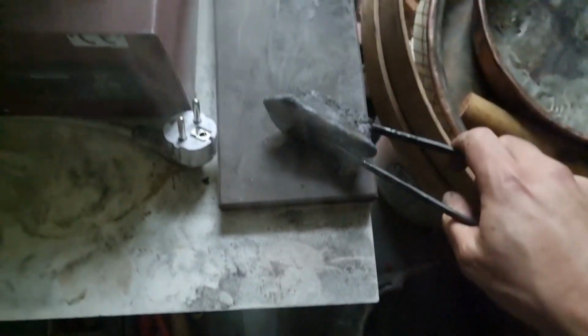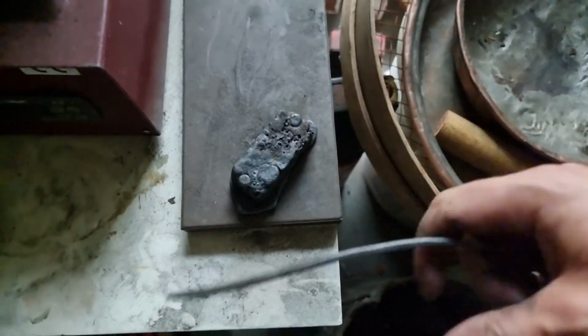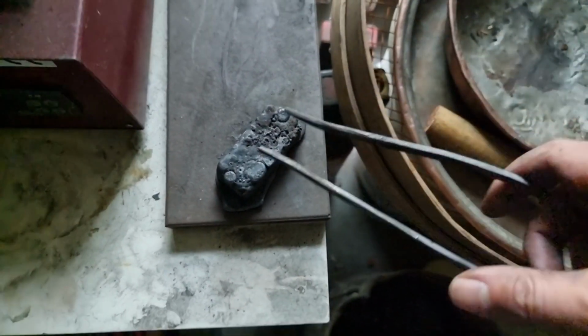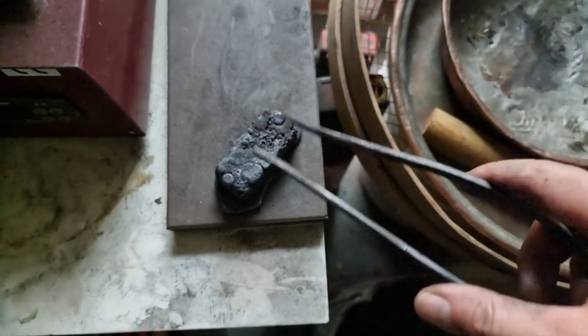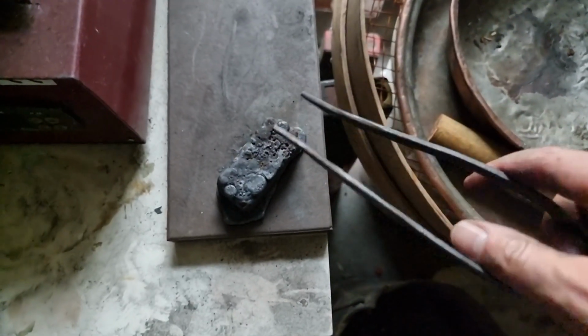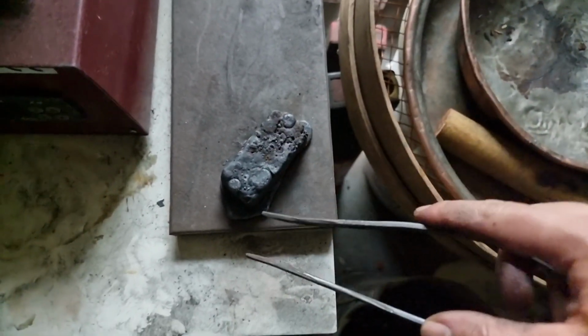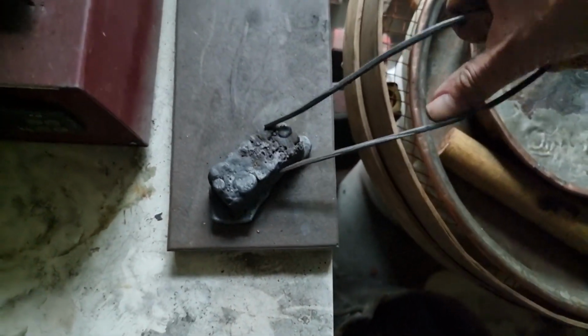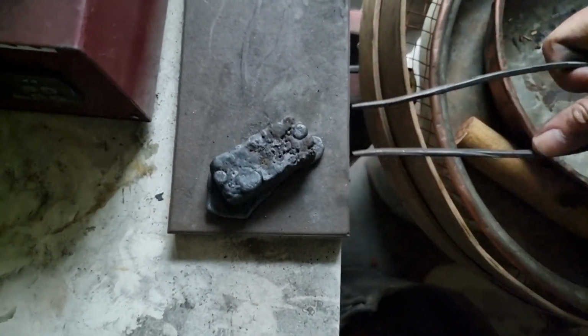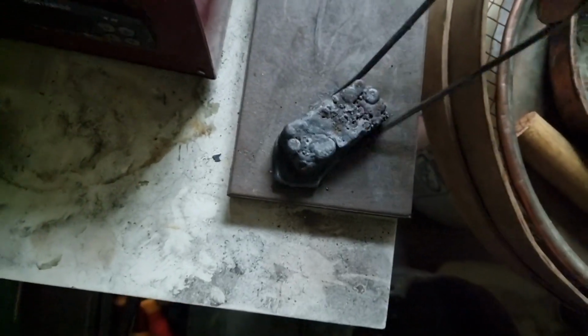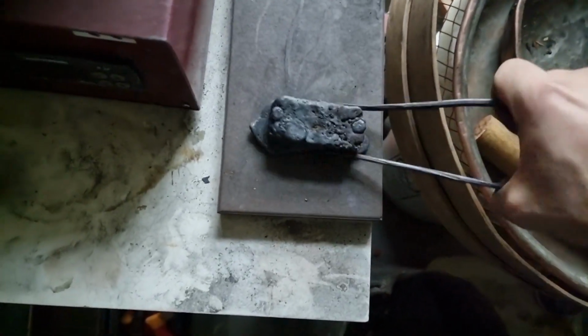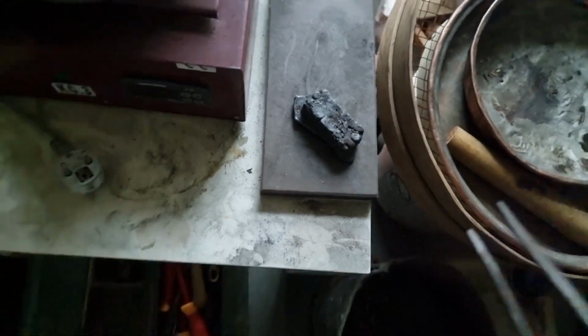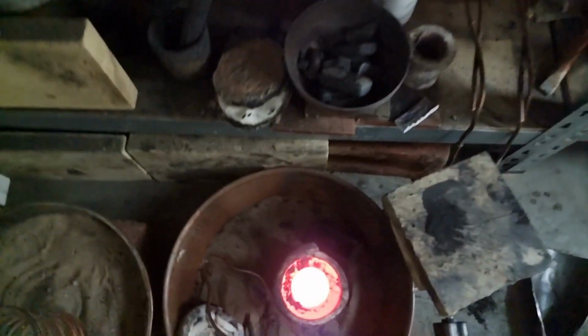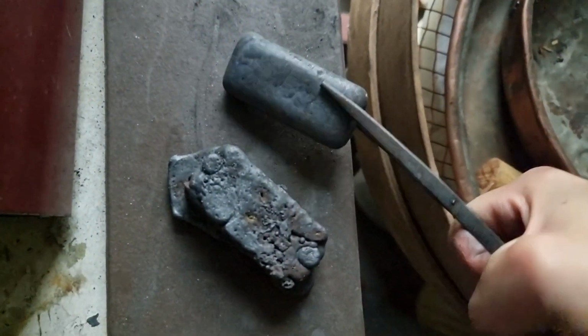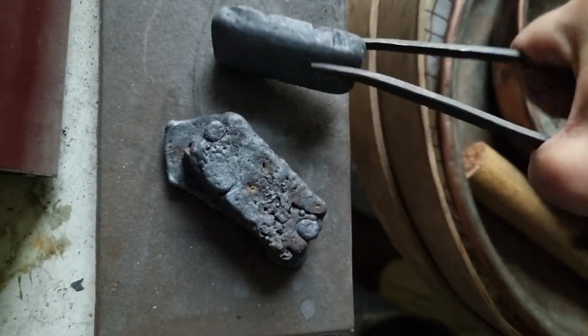That got some temperature. You saw how sticky it was when I attempted to pour out of that crucible. That is usually because there is still some slag associated with that, so it's not really a homogeneous piece of material. But after you melt that again, you typically end up with something like that. That is a much more pure white cast iron.